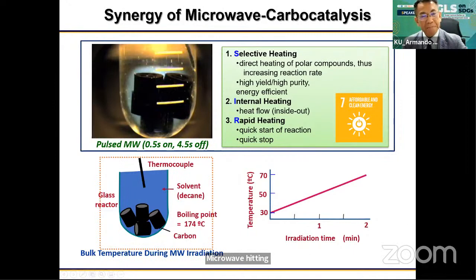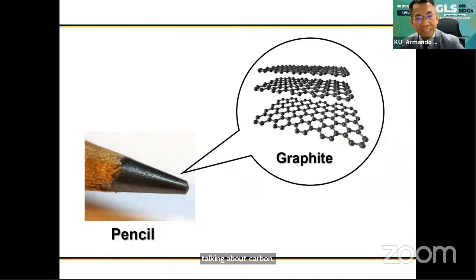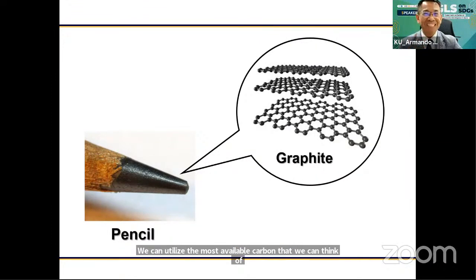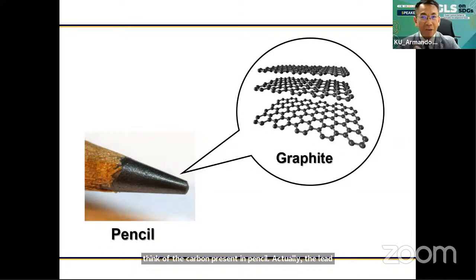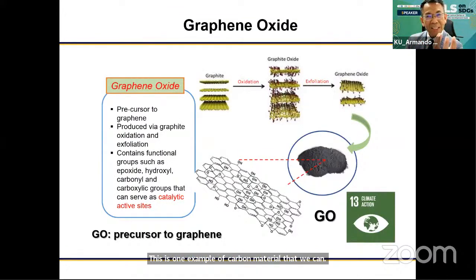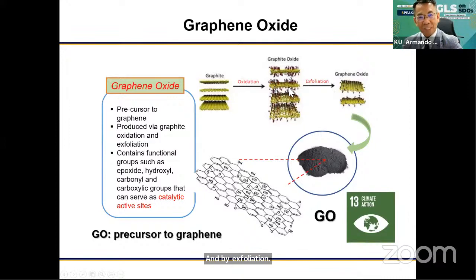Talking about carbon, we can utilize the most available carbon that we can think of, the carbon present in pencil. Actually, the lead of the pencil consists of graphite, which can also be produced from natural materials or from biomass. Graphite. This is one example of carbon material that we can tap. We can convert graphite into catalysts. We call it graphene oxide, by oxidation and by exfoliation. By oxidation, you will get graphite oxide. When you exfoliate it, you get those layers of graphene oxide.